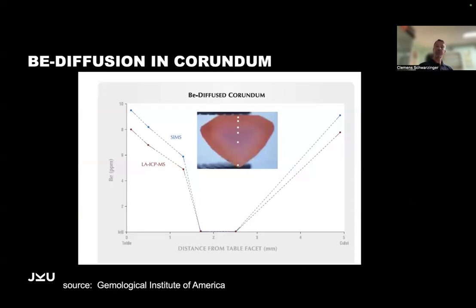In terms of gemology, one of the first things that made laser ablation very famous was the detection of beryllium diffused corundum. In corundum, very frequently you have issues like it's not clear enough, there is rutile silk and so on. So people figured out early on that if you heat treat them to very high temperatures like 1800, 2000 degrees centigrade, you can remove lots of these inclusions and make a little improvement in color. At some point, people were heating other materials as well, one of them being chrysoberyl, and chrysoberyl includes the element beryllium. They had some remnants of this chrysoberyl still left in their furnace, heated the next batch of sapphires, and then found out they turned a wonderful orange.